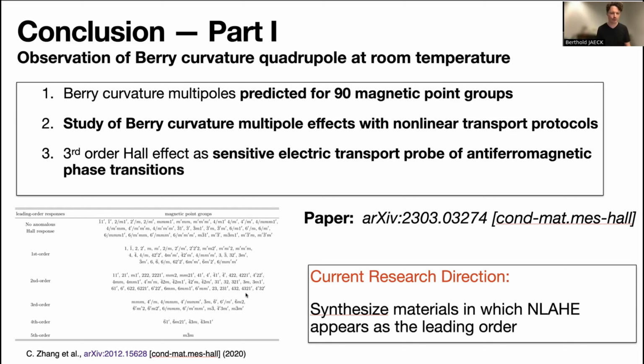So what we have been showing here is that antiferromagnets are a very rich material platform to study Berry curvature multipole effects. As a matter of fact, 90 point groups are predicted to support these multipoles, and the symmetry groups that should support those in leading order are shown here in this table. Now, what we could demonstrate also is that by using Hall measurements, we can find evidence for a Berry curvature quadrupole in spin-canted iron tin at room temperature.